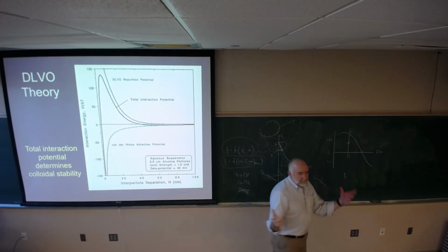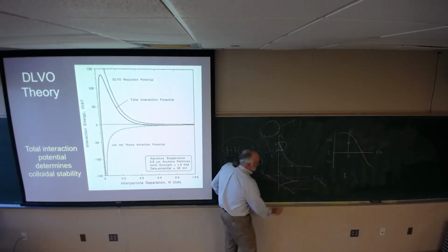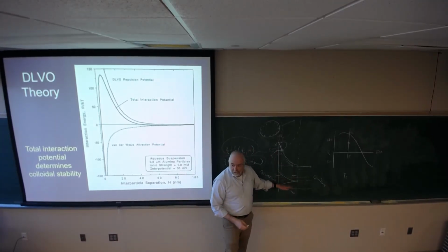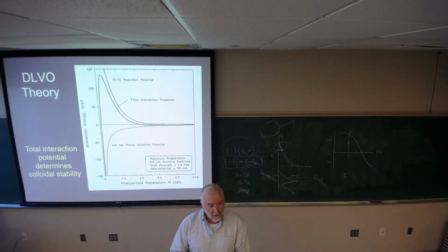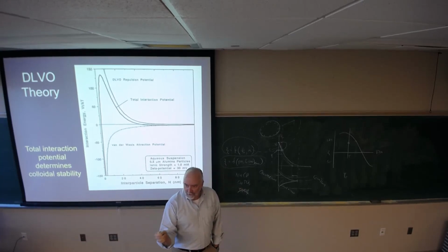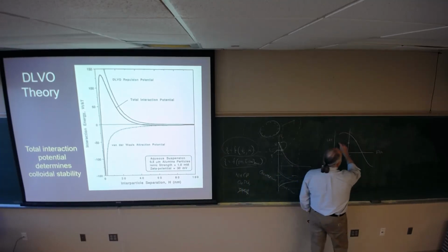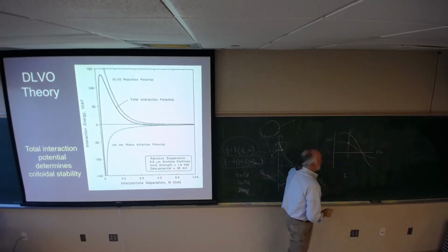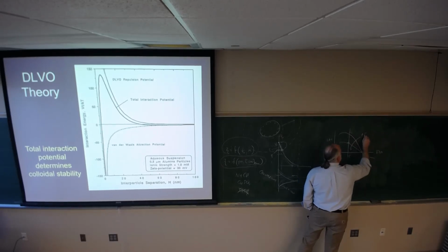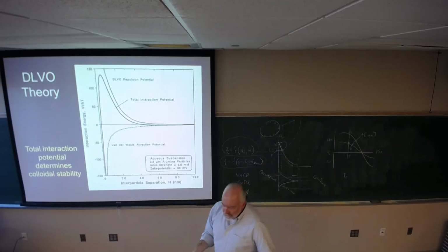So, if I increase the concentration of ions at a given pH, what happens to the zeta potential? It goes down. If I increase the concentration of ions, I compress the double layer, and I decrease the zeta potential. In the absence of specific affinity, meaning that I have an indifferent electrolyte, the curve does not shift its isoelectric point, but the zeta potential decreases. This is for an increase in the bulk ionic concentration. Zeta potential will decrease.